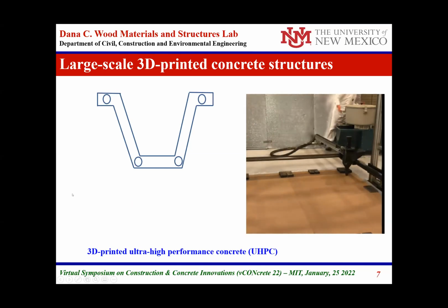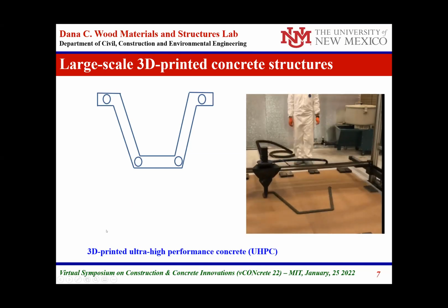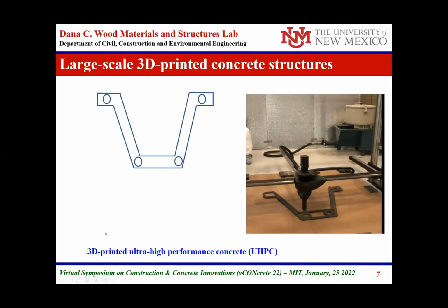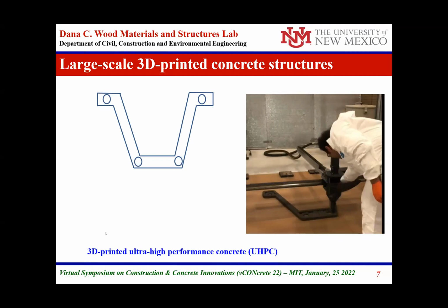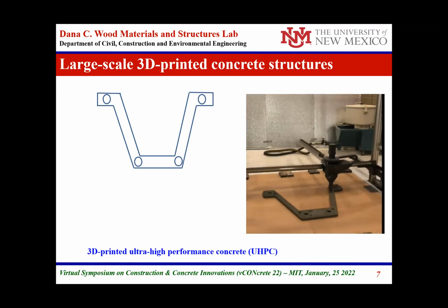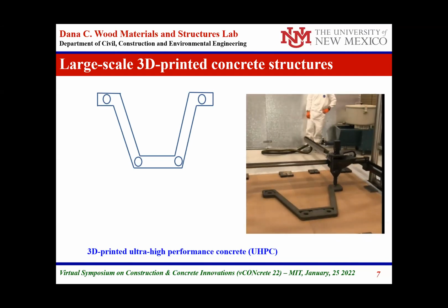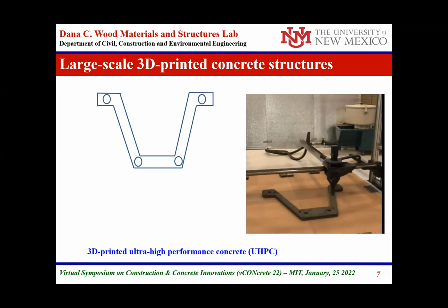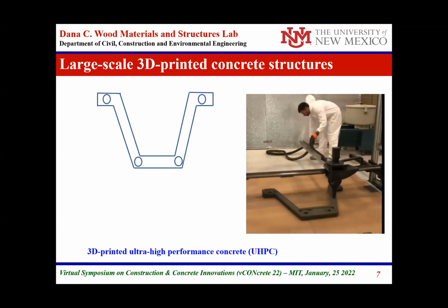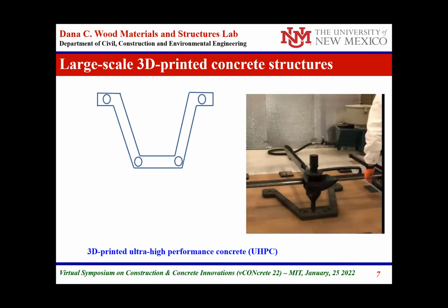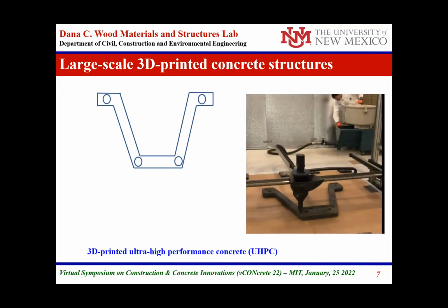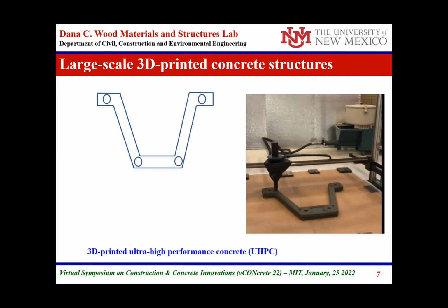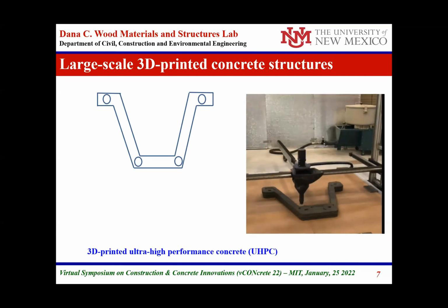This is an example of a 3D printed trapezoidal box girder bridge that we printed in our lab. This is a concrete that is about 10,000 psi, about 70 megapascal strength. An example cross-section, about 1.5 feet high, was printed in about 1 hour. So you can basically print a good part of this bridge in a day, and then the rest is the post-tensioning.